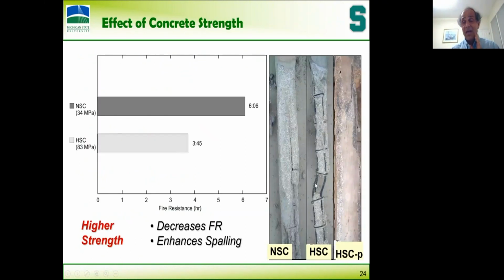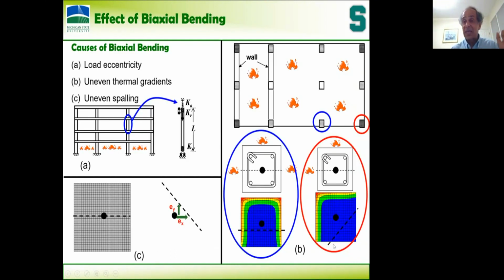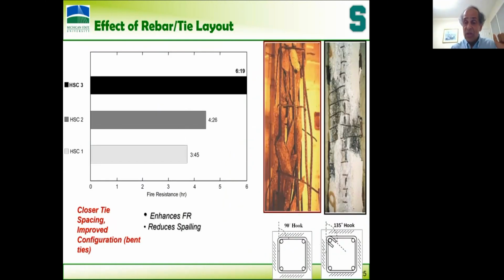As you can see, with higher strength concretes compared to conventional concretes, if you add fibers, you can significantly minimize this spalling which is happening. Okay, another thing is if you bend the ties, it enhances fire resistance significantly. Bending the ties at 135 degrees, this we did for PCA and this is in American codes right now. You can reduce spalling significantly even with higher strength concretes.